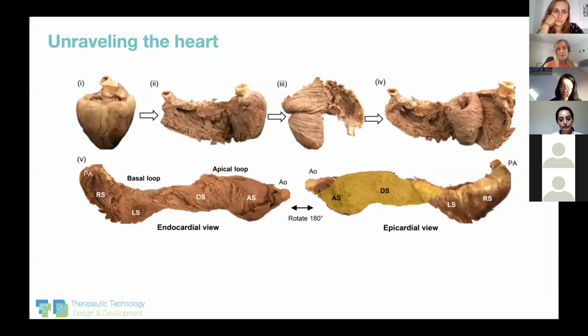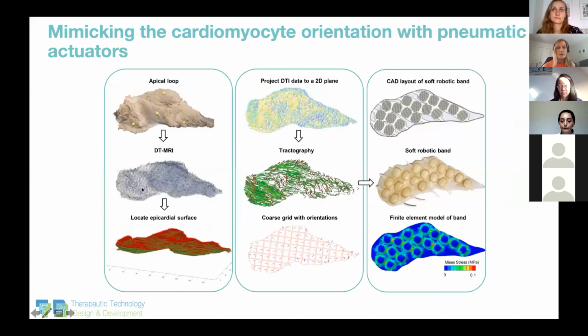But as I mentioned, we wanted to make this active, and just to go through this myocardial ventricular helical band a little bit more. This is the heart, and this is, as you start to unravel it, what it looks like. So you do this in a very systematic fashion. And then you end up with this band, and you can identify the parts that form the left ventricle, which is the active part we wanted. So we just isolated those parts that form the left ventricle, and we went to the scanner.